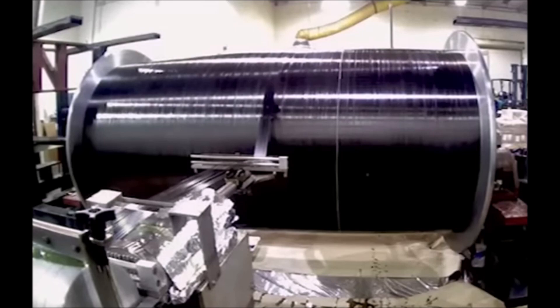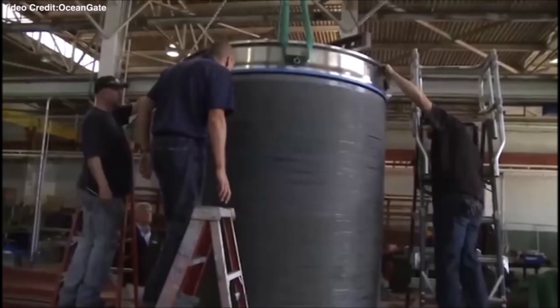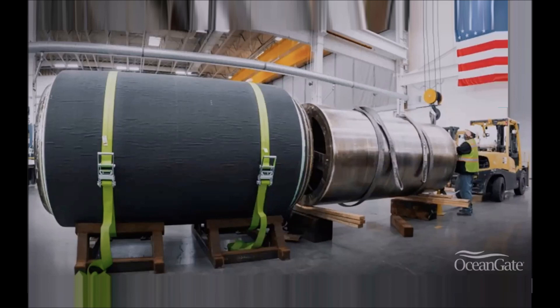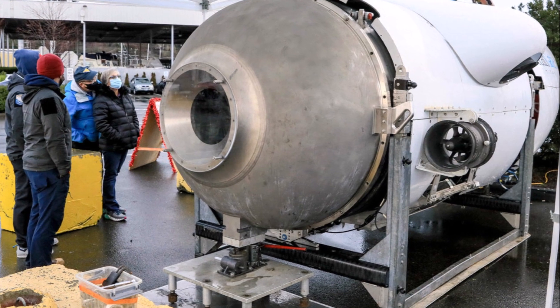As we saw earlier, the 2017 hull never stopped making noise and was scrapped — it truly suffered on every dive. I would have expected that one to fail just from seeing how it was manufactured. According to Bruce Morton, the former OceanGate engineer, the 2020 hull made some noise on the first dive and then was quiet on the dives that followed. Rush stated: 'If we can listen in and hear those fibers breaking, we can know ahead of time if it's going to fail — we use that as a predictive process. The first time we tested the hull in a hyperbaric chamber, we could hear those fibers breaking. But then on all successive dives and tests, it was quiet. We kind of worked out all the kinks.' That was the expected outcome.